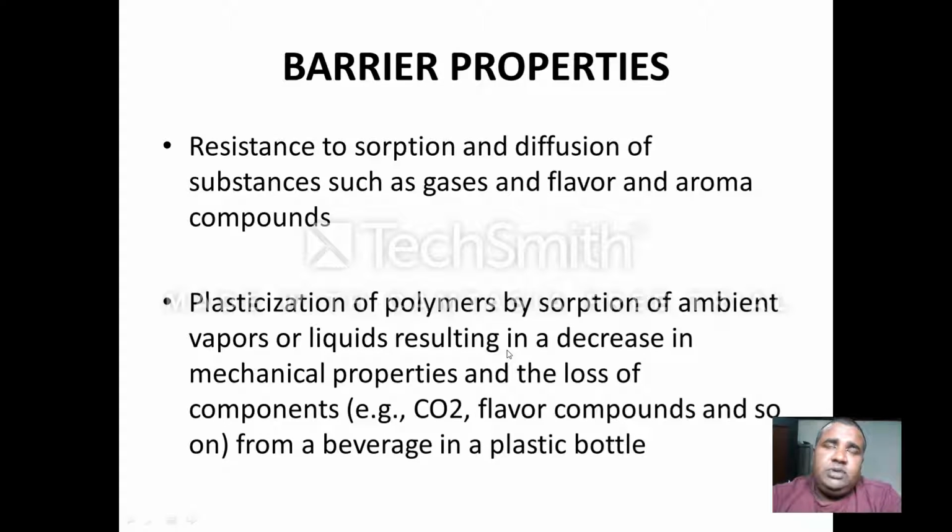So if your packaging material is not a good barrier to gases or water vapor, it can lead to plasticization. Plasticization is simply a process of swelling of the polymer when a certain amount of water vapor or any solvent has been absorbed on the surface. The second problem can be the loss of a component, for example CO2 or flavor compounds and so on, from beverages in plastic bottles.